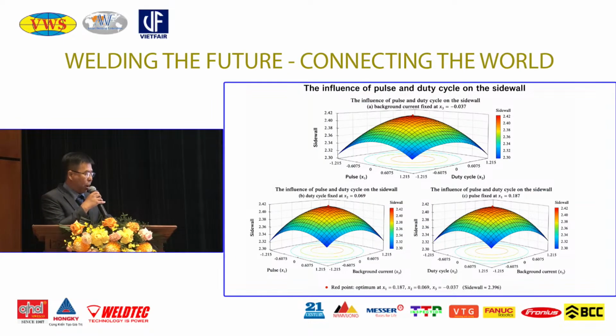The interaction between pulse current, duty cycle, and background current is evaluated by fixing one parameter at its optimized value, based on the evaluation result of Q355 steel weld using Hồng Ký 350 RS Pro. While one parameter is kept constant, the variation of the other two parameters is analyzed in relation to sidewall penetration. As shown here, the response surface shows how their interaction affects the sidewall. The approach allows us to identify the optimized region and confirm important parameter interactions.